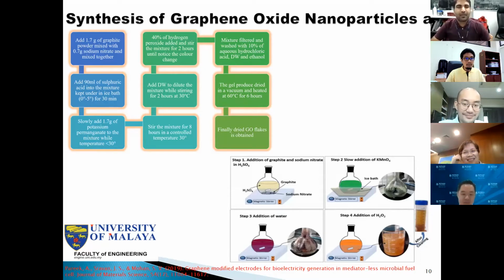No worry. Okay. So for the synthesis of graphene oxide, we were using a modified Hummers method. This is the flow of the synthesis. Basically, we have the raw material, graphite flakes, then the strong acid, sulfuric acid, then potassium permanganate, and according to the required percentage, we add it, sonicate, mix, and stir it, and after passing all these three steps, we come up with the final product in the form of graphene oxide nanofluid.